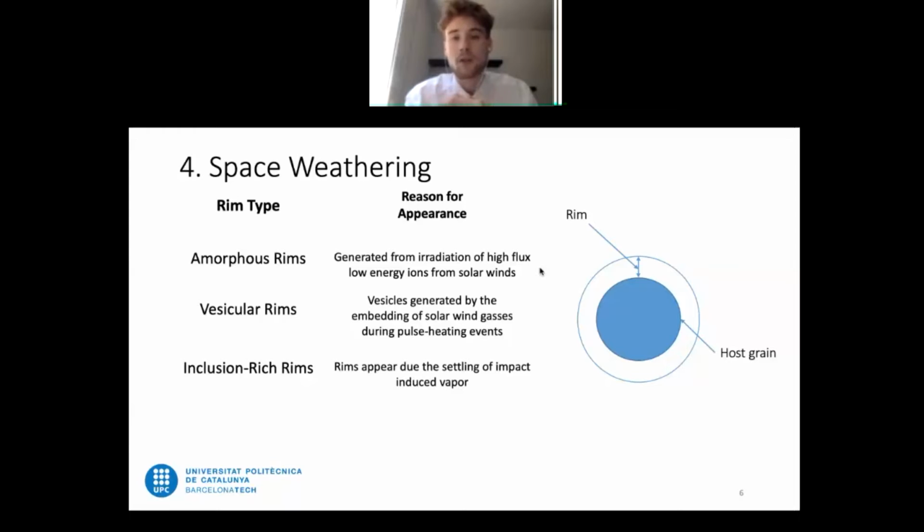As the iron oxide, compared to the other oxides which are present within the lunar regolith, has the weakest binding energy, the hydrogen acts as a reduction agent, which then reacts with the oxygen attached to the iron element, effectively reducing the iron down to its metallic constitution. Therefore, once the vapor condenses and settles, we have this glass-like material, and we will see the metallic iron being present within this glass type substance.